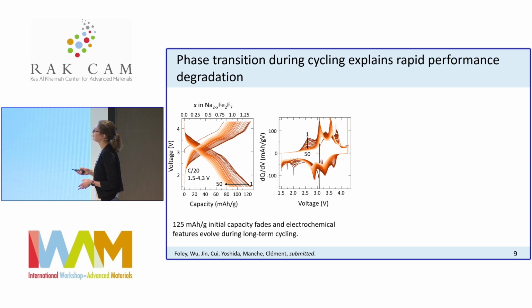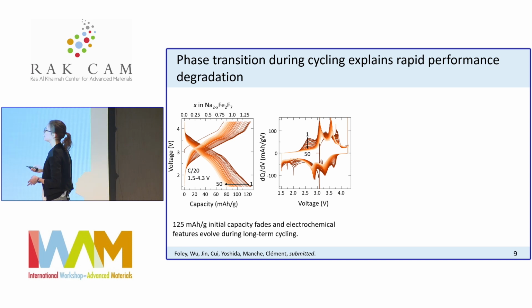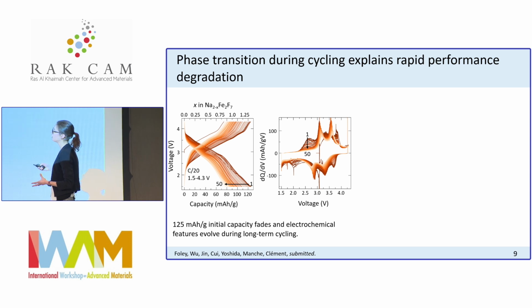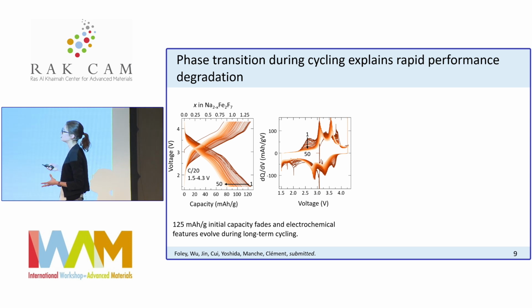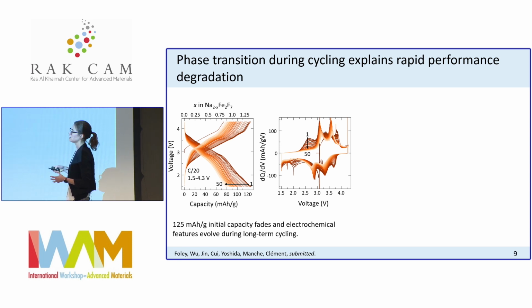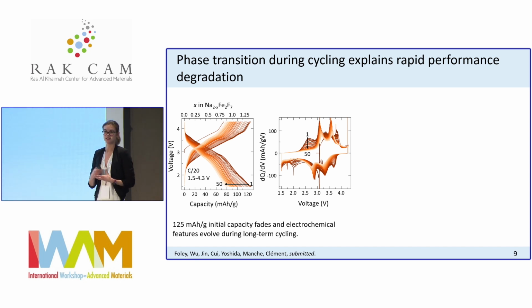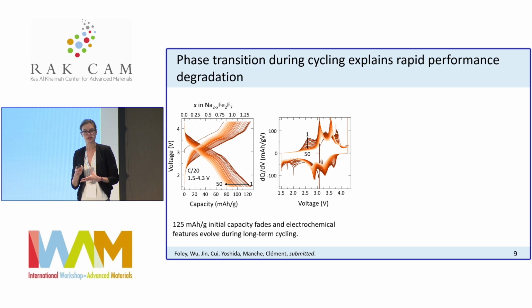Another way to look at this is to take the derivative of this curve. So you take the derivative of the capacity with respect to voltage, and you plot it against voltage. What that tells you is where the redox processes are happening, at what voltages they are happening. And what you can clearly see from this plot is that the redox processes evolve with cycle number. So clearly there's something changing in the crystal structure that's leading to these changes in the electrochemistry.